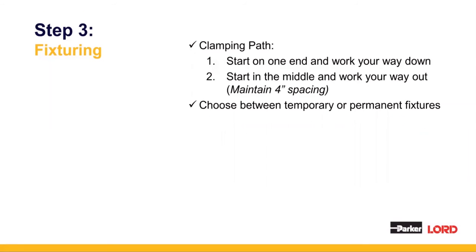This could cause the part to bow slightly in areas between the clamps, resulting in poor adhesion in some areas and even stress concentration in other areas. Air also becomes entrapped when your parts bow. So it's important to know that handling strength will vary depending on the size and the weight of your parts. The heavier and bigger the part is, the more handling strength you'll need. A great place to start is our handling time rating and our tech data sheets, which you can download off our website, lord.com.